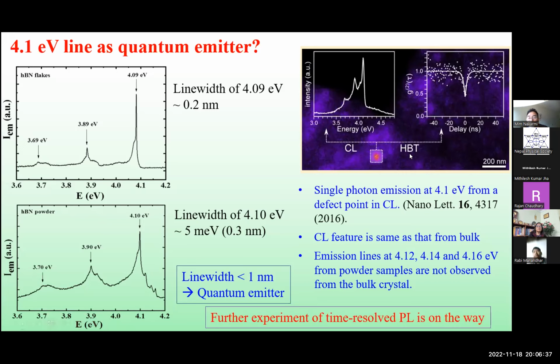So we don't have this experimental setup, and we did not perform it, so we cannot claim our emission is a single photon emission. But our emission is exactly the same as theirs, and our emissions are very narrow. So the origin of our emission and the origin of this reported one should be the same. That's why we are saying it is an atomic-like emission. We cannot claim it's a single photon because in the photoluminescence system we excite the material with a laser beam, and the laser beam diameter could be like 1 millimeter, and this spot is maybe 50 nanometer.